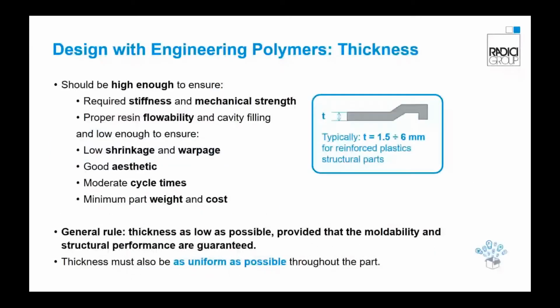Here are some hints on how to approach the design with engineering polymers. First, we take a look at the part's thickness. Thickness should be high enough to ensure required stiffness and mechanical strength of the part, but also, from the process point of view, to ensure proper resin flowability and cavity filling. At the same time, thickness should be low enough to ensure low shrinkage, good aesthetics, moderate cycle time, and minimum part weight and cost. As a general rule, thickness as low as possible, provided that the moldability and structural performances are guaranteed.